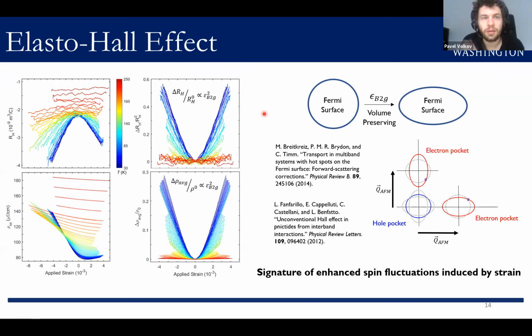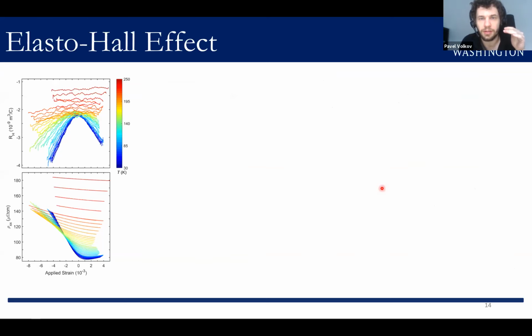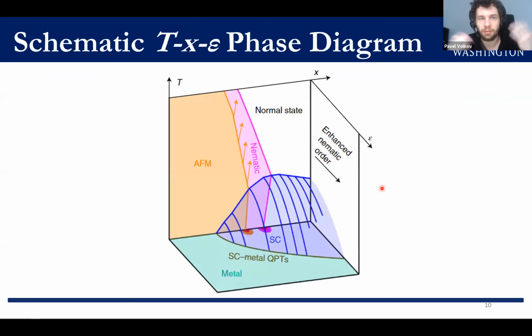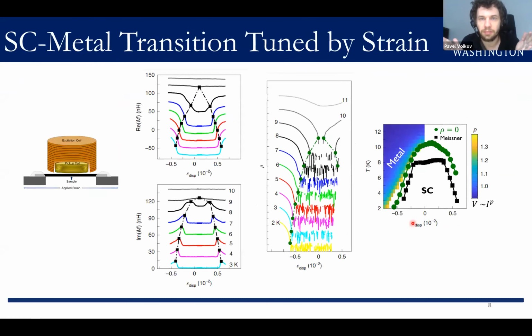Yes, when you compare TC obtained from Meissner and resistivity in the low strain region, it seems that the resistivity transition kicks in quite a bit above the Meissner transition. Does it suggest that, with the formation of domains, perhaps the superconductivity at the domain boundaries is occurring at a higher temperature than in the bulk without the domain walls? I'm talking about the low strain region. So I'm wondering whether that tells me that the superconductivity between 10 and 8 is due to domain walls or something like that.